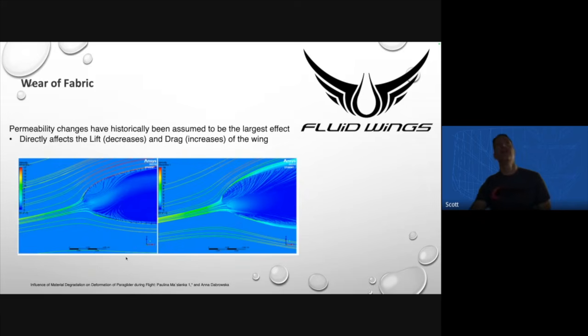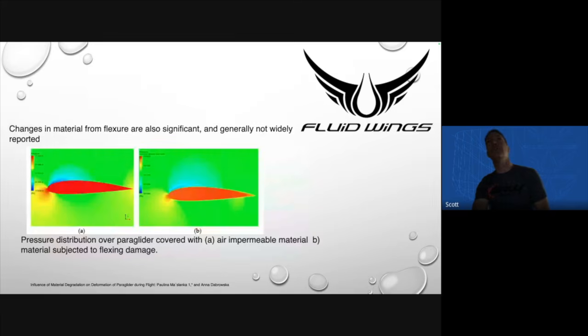You see on this left one, the pressure is being contained very nicely. You look at the boundary conditions; they're really clean, right on this leading edge. You don't see any separation, vortices, stuff like that. What happens on the permeable fabric over here on the right side is it goes in, and then you see the flow lines. It's actually starting to flow outside, and then you see a separation on the leading edge surface there. Happens to be where most of your lift is produced. Most of the lift is on the front part of the wing, guys. The first 25% of the chord produces probably 70–80% of the lift. Estimate, don't hold me to those numbers. It's just a ballpark and depends on the airflow, right?